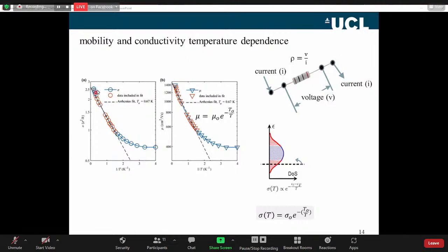What we found is that the conductivity is thermally activated. So what's happening is, this is the valence band here, and this is the hole energy, so these are positive hole energies now. This is the band gap, this is the hole energy. This is the chemical potential, the dotted line here. And what we're seeing is a thermal excitation to a mobility edge. So the carriers have to be excited to this point in the band to conduct. So it's a thermally activated process.